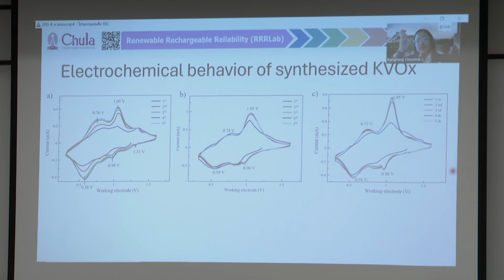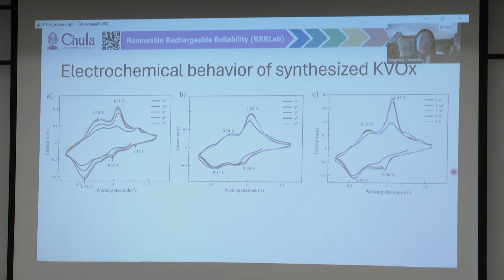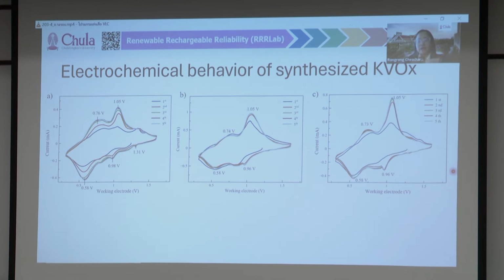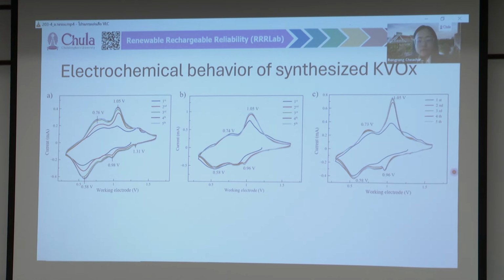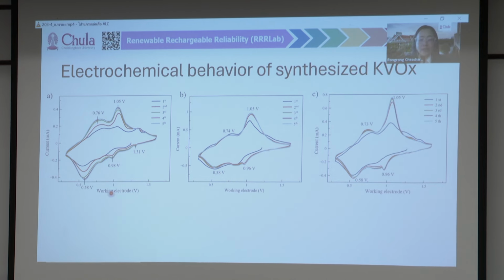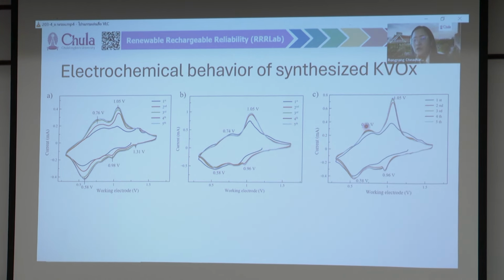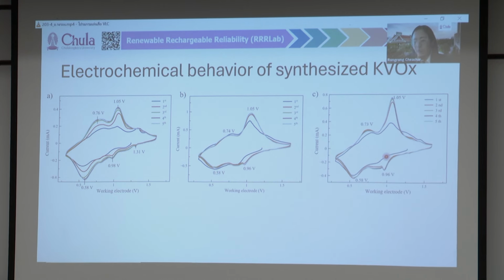So we mix the cathode materials with conductive carbon and binder, and then we put it into a coin cell, CR2032, in a zinc sulfate electrolyte, and then we measure the cyclic voltammetry. We found that the oxidation and reductions for the control one are slightly different, of course, because it's a different phase, but there are more redox reactions for the control as compared with the one synthesized at pH 3 and pH 5 here. But these two are quite similar, but the pH 5 one seems to be slightly better in terms of the reactions.